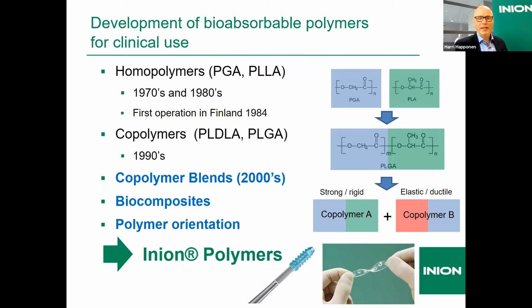However, those implants were still brittle, and what we at Inion started in 2000 was copolymer blending. We mixed a strong and rigid polymer with an elastic, ductile polymer to make the implant both resorb in a suitable time frame and change the brittle properties to ductile properties. During these 20 years, we have also launched biocomposite materials and a polymer orientation process to make the implants even stronger than previously. We call that polymer technology Inion polymers, or Inion polymer technology. And then we will see more about that in the coming slides.